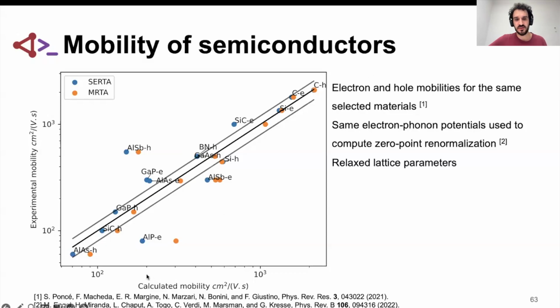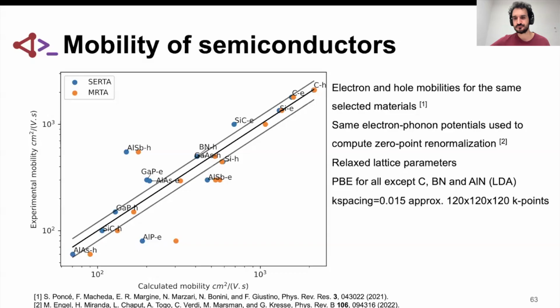What we are showing in this plot is the calculated mobility versus experimental mobility, and we can see that the agreement is quite good. In general, PBE is used except for carbon, boron nitride, aluminum nitride, where LDA is used. These are the parameters of the calculation.